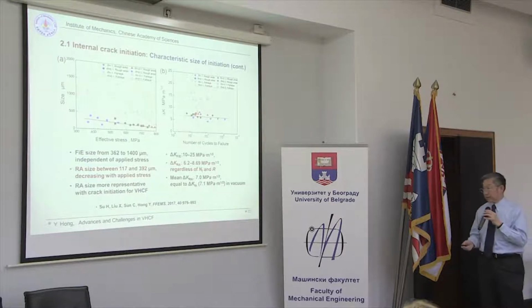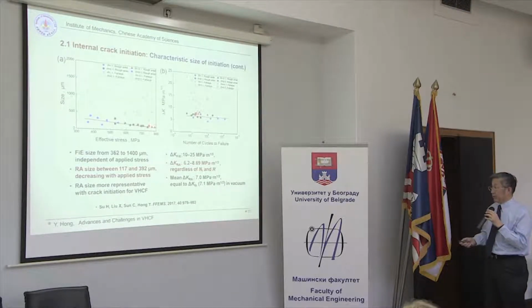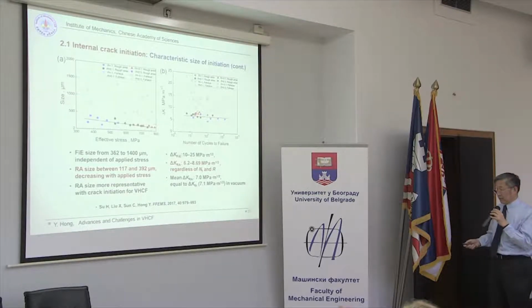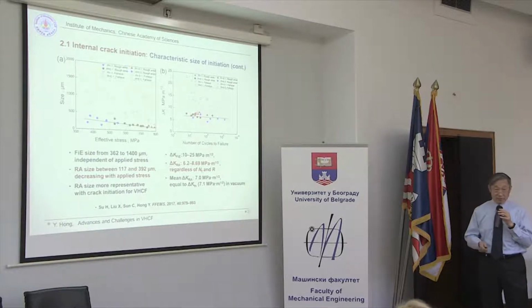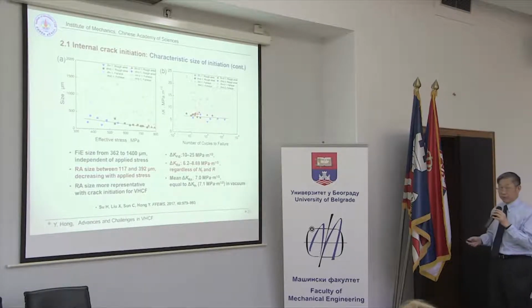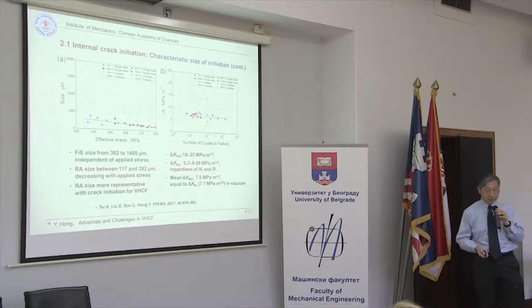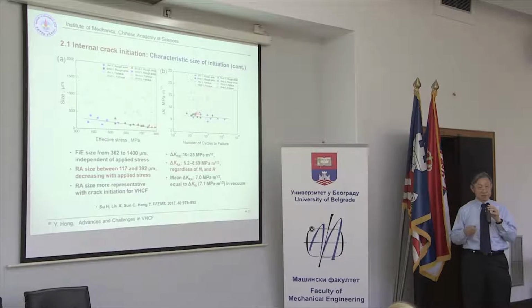And for titanium alloys, we also measure the size of FGA of the eye region, and it's between about 120 and 390 microns. It's still quite within a certain range. And the value of delta K is between 6 and about 8.7 megapascal root meter. That is also similar to the case of high strength steel. It's quite stable. So this type of phenomenon is not just for high strength steel, it's also for titanium alloy.